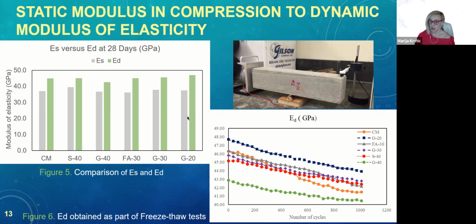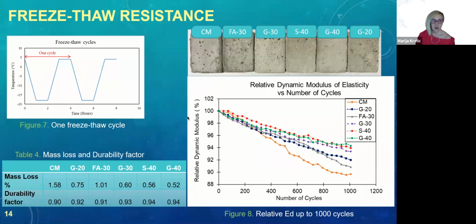After curing for 14 days, we tested for initial dynamic modulus, and then we were checking up to 1,000 freeze-thaw cycles. One freeze-thaw cycle as per ASTM C666 was 4 hours, where temperature goes from +4 to -18 degrees Celsius and goes back to +4. So all this happens in 4 hours, and per standard, the maximum number of cycles allowed at once was 36 cycles. So after every 36 cycles, we would check samples visually for deterioration, and we would also weigh them to check the mass loss and check dynamic modulus of elasticity.